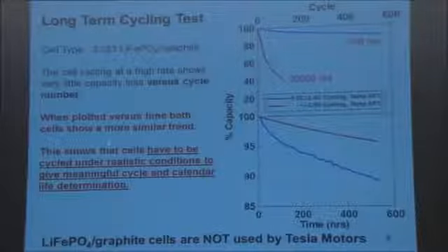So the point is that you get a lot of capacity loss versus cycle number when you go slow at high temperature, because there are chemical reactions going on in the cell that are bad. And when you charge-discharge rapidly, all you're doing is beating the clock. You're beating the clock on these temperature-dependent, time-dependent parasitic reactions.